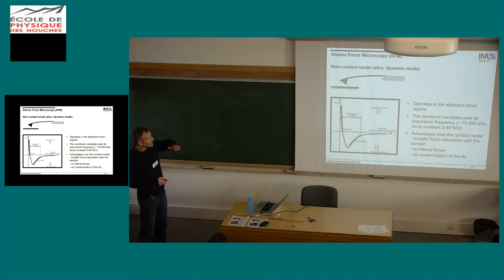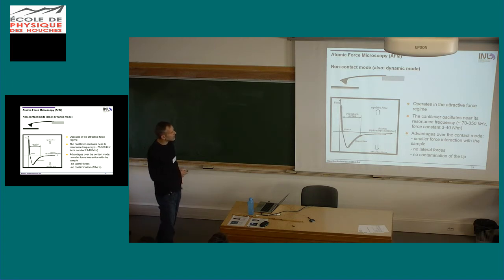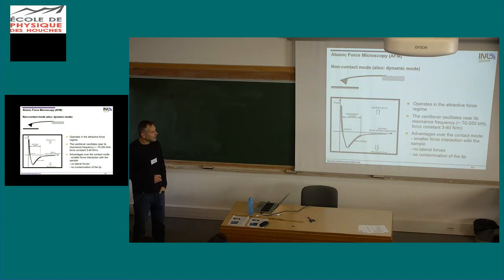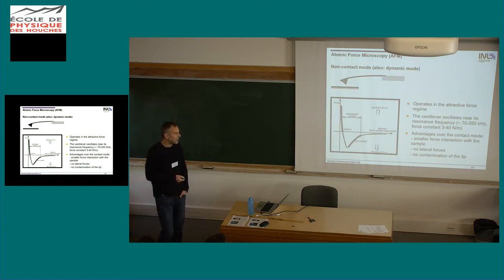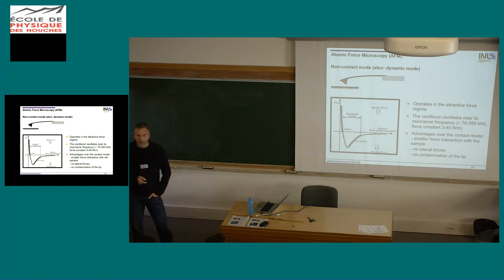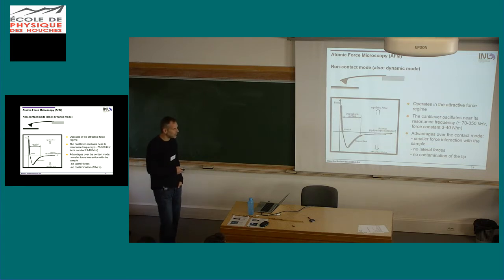We are just above the surface at some distance, and we oscillate the cantilever at or close to its resonance frequency. Typically we use stiffer cantilevers, so they are not as soft as the ones in contact mode. And the resonance frequency is somewhere between 100 kilohertz and 1 megahertz, depending on what kind of cantilever you use. So this tip oscillates at this frequency.